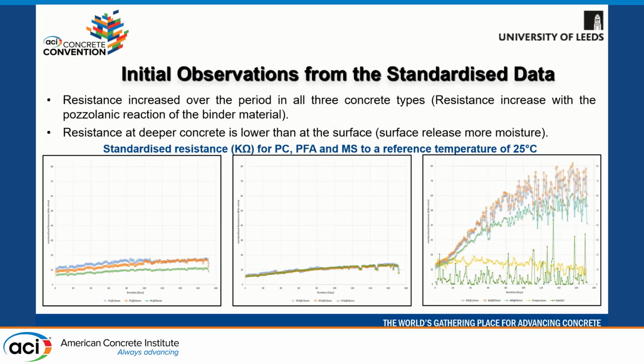So the initial observations from the standardized data were that resistance increased over a period of time in all three concrete types. That is because resistance increases with the pozzolanic reaction of the binder material. Also, microsilica increased at a faster rate than PFA and PC because addition of supplementary cementitious materials alters the pore structure due to the pozzolanic reactivity. Finally, resistance at deeper concrete is lower than at the surface because surface is releasing more moisture while the deeper part is saturated, and evaporation of moisture leads to increase in resistance.